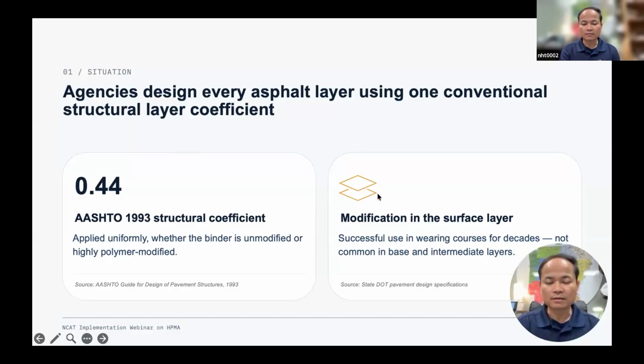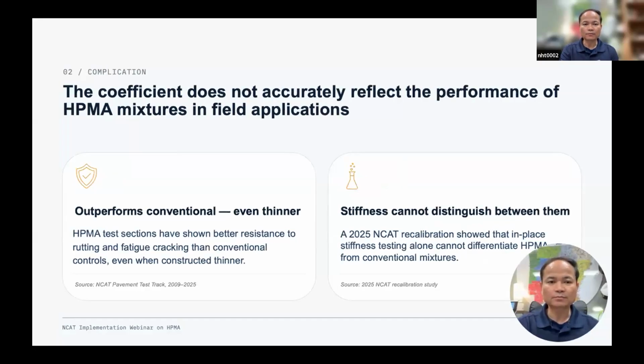Another thing that is very commonly done is that polymer modification is used in the surface layers. And this has been a success for many decades. However, it's not common to use polymer-modified asphalt in the base and intermediate layers. And that really creates a gap between the current design practice and the actual field performance of that mix. I'm going to talk more about that based on the experiments at the test track. So for the reason I stated before, the current pavement design practice does not fully take into account the HPMA, the polymer modified asphalt performance.